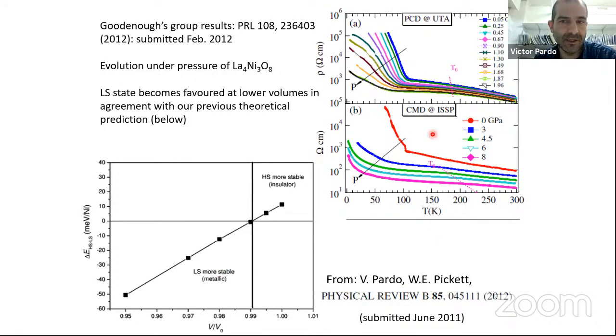So a few months later, Goodenough's group did the same thing with their samples. They pressurized them, and what they saw is that indeed the charge density wave transition goes away, and the system moves to a more metallic situation. They don't reach the actual metallicity because the system undergoes a structural transition, but that's a different story. So okay, when you reduce the volume of this compound, you get something closer to a metal. But pressurizing materials is not that easy to make.